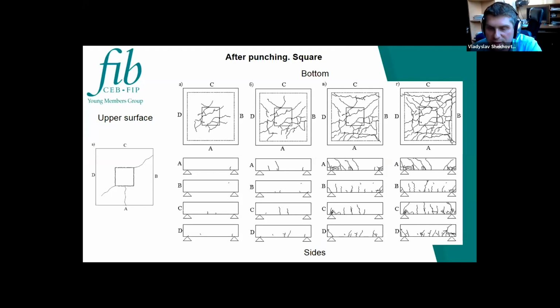upper and bottom surfaces. Here we present patterns for 25, 50, 75, and 95% of failure load steps. You see the punching crack, the beginning. It is 95% before collapse. We see the forming of the punching crack, which started to collapse with the pyramid cone.